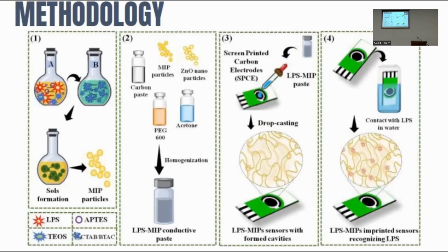The second step consists of a lab-made LPS MIP conductive paste formulation prepared by continuous homogenization of the embedded MIP particles with zinc oxide nanoparticles in acetone, followed by a commercial carbon paste and polyethylene glycol addition. LPS MIP sensors were developed by drop casting deposition of a small quantity of LPS MIP conductive paste on commercial ceramic screen-printed carbon electrodes, corresponding to the third step. The last step consists of recognition and rebinding assay of LPS molecule in aqueous matrices.